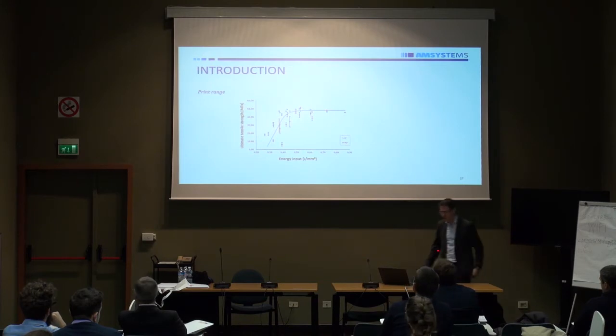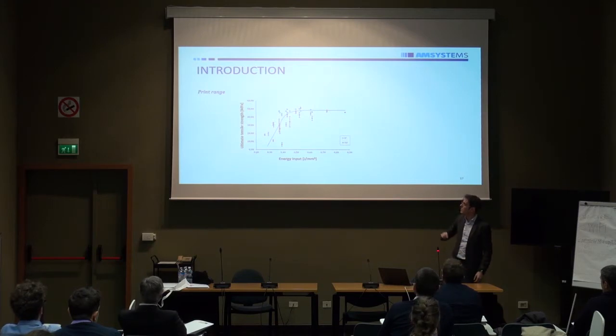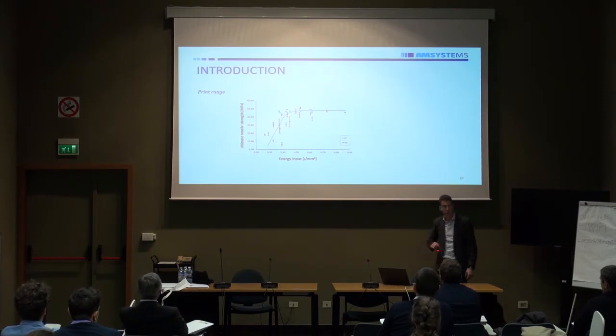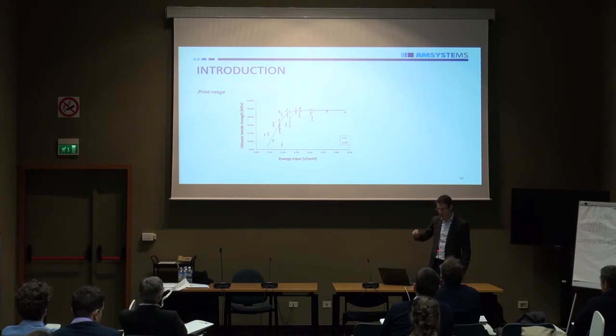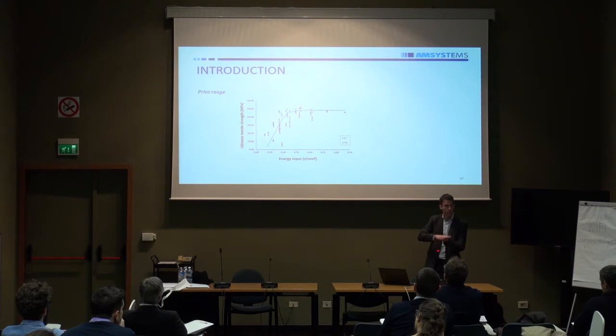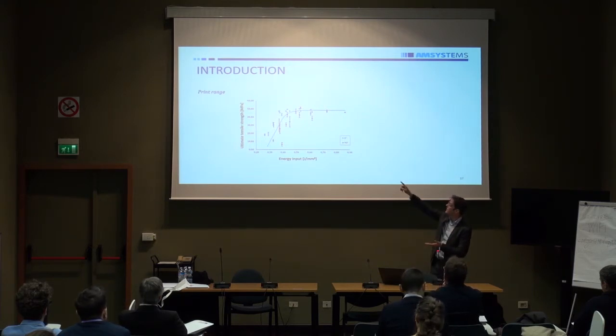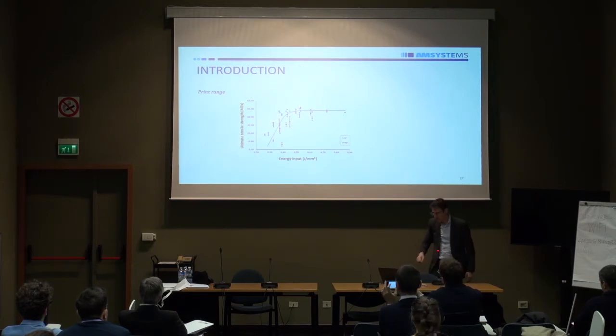So what we put in this graph is on the horizontal axis the energy input. For example, you can change the laser power, and on the vertical axis you have the tensile strength of this tensile bar that we printed. And what you see, if you have a very low energy input, then the layers just really don't stick to each other. And if you put it really high, then of course you go to an optimum. But why not go to a very high value? I will show you why.